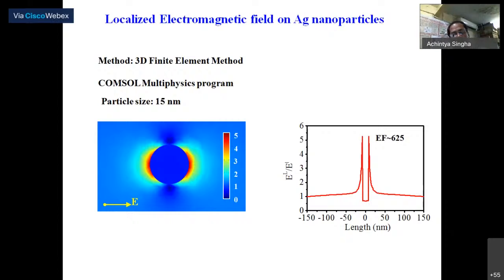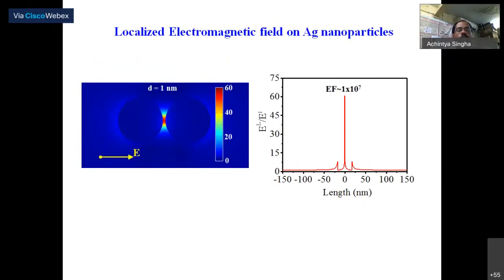But if you make a dimer like that, go next. In a dimer, you can see this enhancement at the gap between the two nanoparticles. If it is a very narrow gap, then there will be a strong hotspot. This is called a hotspot. And on the right side, you can see the enhancement is of the order of 10 to the power 7.